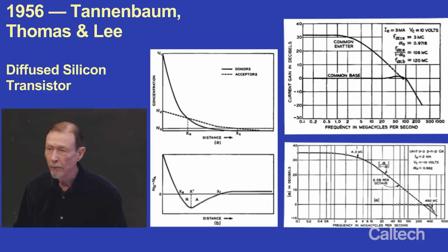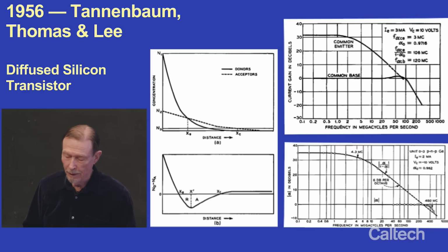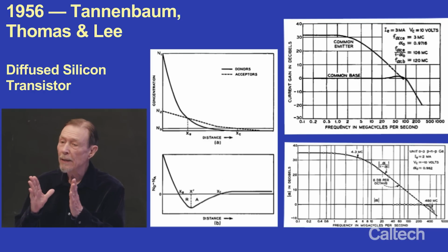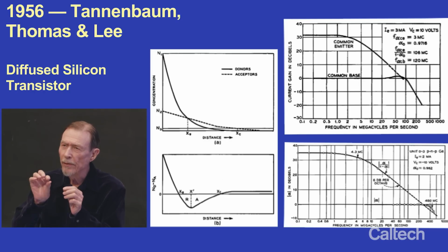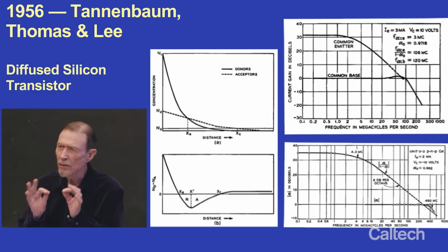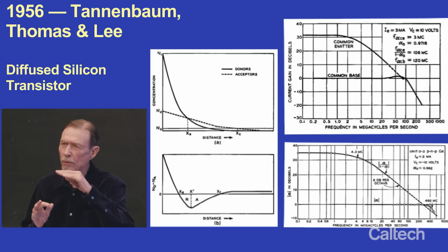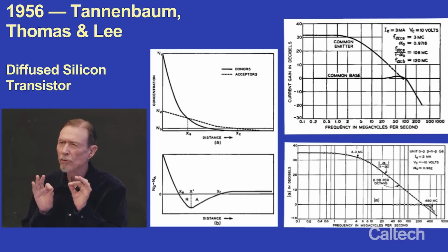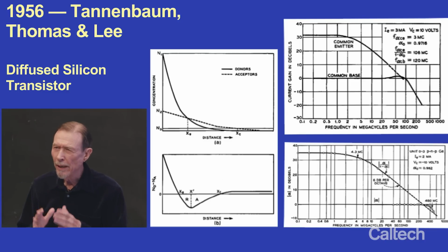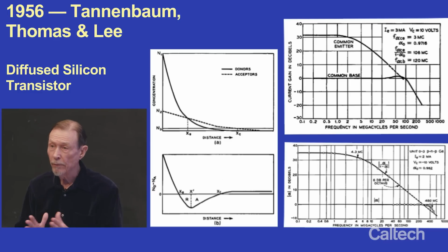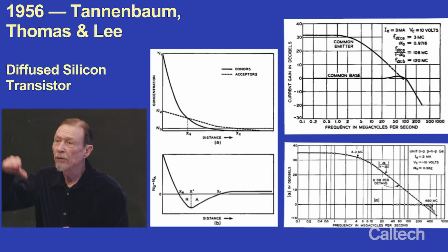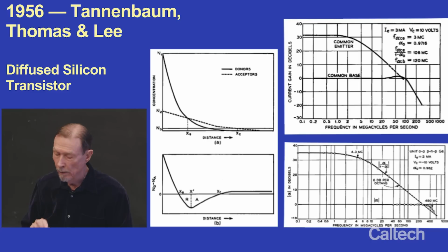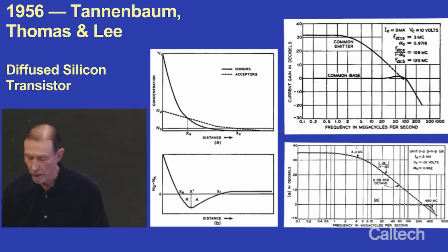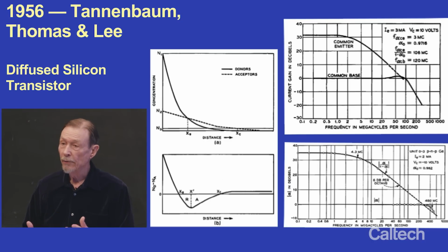Well, electrons in silicon go faster than holes do. So this was a fast transistor, and you can really control the depth of the junctions by this diffusion process, which is just a chemical process. You raise the temperature a certain amount and the diffusion happens at a certain rate, extraordinarily well controllable, down to fractions of a micron. So you could make a transistor that had submicron dimensions vertically by this diffusion technique. And all of a sudden, the transistors, instead of being 70 megahertz, were 400 megahertz. And silicon had bypassed germanium as the speed record.